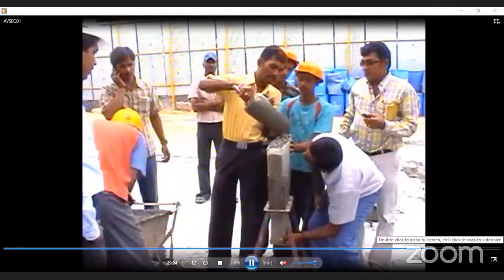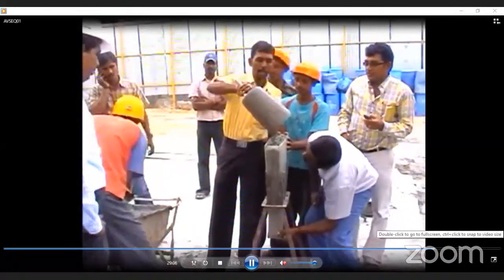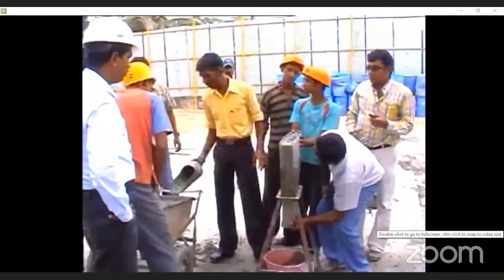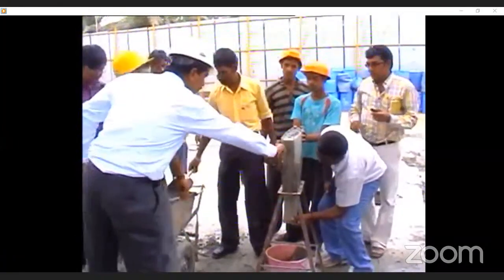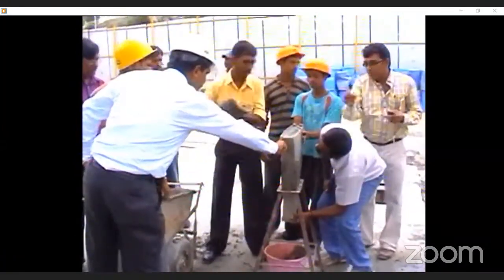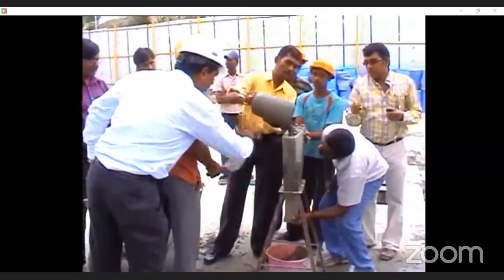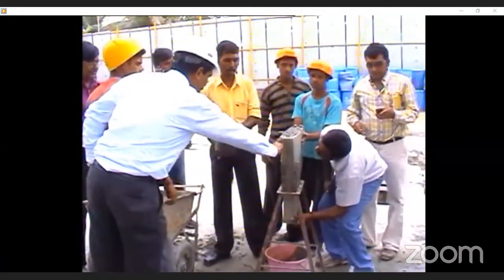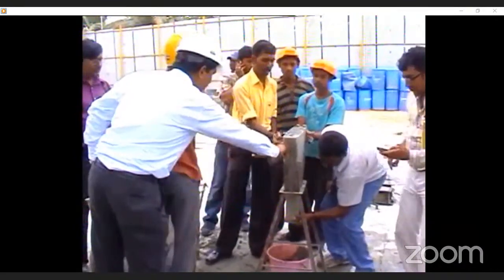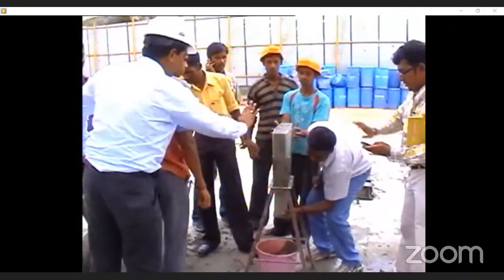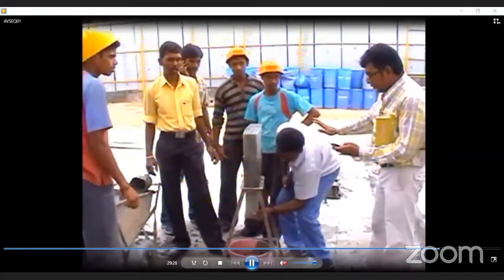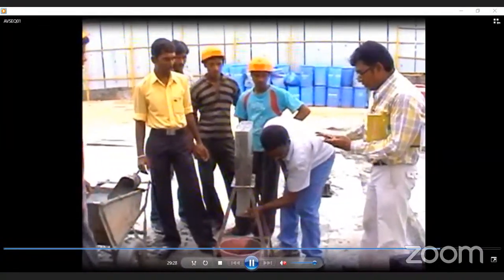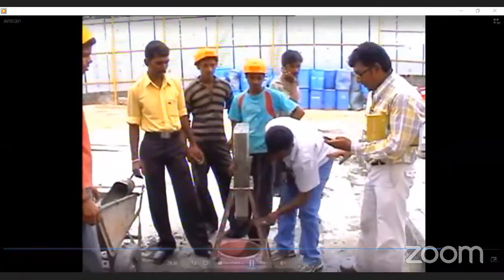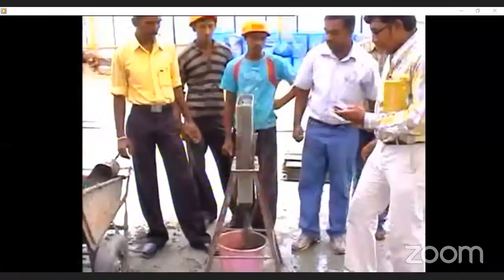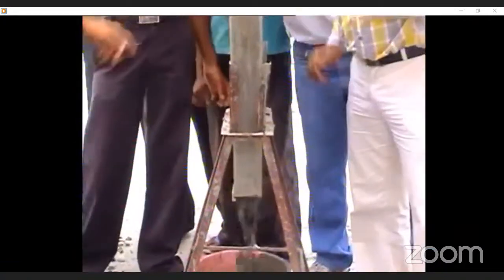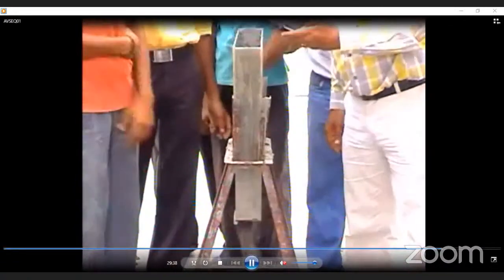This flowable concrete or SCC has different requirements: fillability, flowability. Flowability means it should be able to pass through the reinforcement. Fillability means it should fill each nook and corner of the formwork. Like that, we have different requirements. It is not a single requirement. Now, the entire concrete in the V funnel should have passed in 10 seconds. We achieved somewhere around 8 seconds.